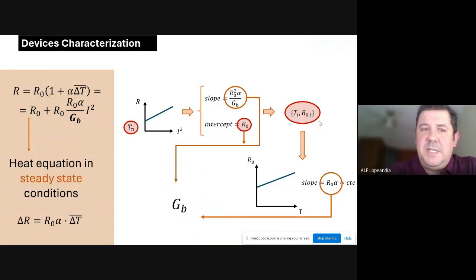What is the measurement? The initial measurement that we have to do is to calibrate the temperature coefficient of resistance, and for that reason we do the staircase. We can extrapolate the resistance here. Now we do the staircase of currents. We measure the different resistance for each one of the amplitudes, and we can extrapolate the resistance at zero heating, I would say, without self-heating. And this R0 can be plotted as a function of temperature, and that permits us to calibrate the variation of resistance as a function of temperature. This is the first.